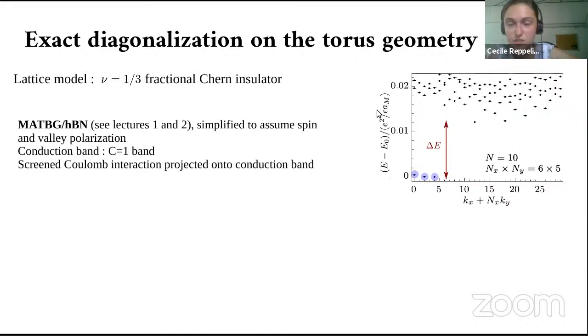So this is the low energy spectrum. Again, I'm labeling all my eigenstates with a momentum, and here you see I have a linearized momentum. On the lattice, I have kx and ky quantum numbers. I could represent the spectrum in this 2D space, but to avoid having a 2D curve plot or something like this, I'm just linearizing it to have everything on one line. So those are my 3 almost degenerate eigenstates separated by a gap from higher energy excitations, which is a sign that I'm in the same phase as the low-field 1/3 state.